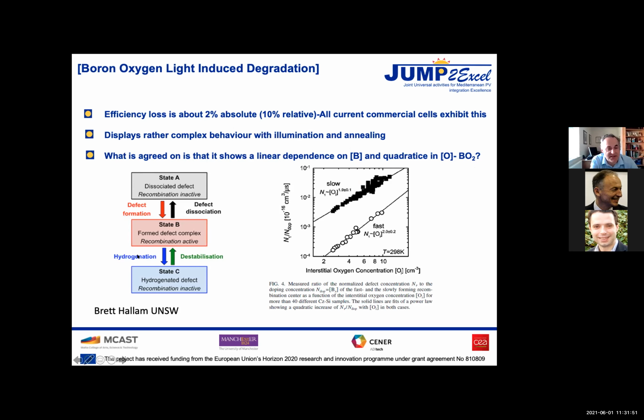This is Brett Hallam's more recent work, looking closely at the states. And it looks as though there are three states, and you can move between them by various annealing processes. So annealing at 200 degrees destroys the recombination active defect. We know that, but it doesn't destroy it, it resets it, and then it reforms again when you illuminate, so you don't get around it that way. Hydrogenation does kill it, but it seems to be quite unstable. Hydrogen doesn't bind very well. So there's quite a lot known behaviorally about it, but not what it actually is.